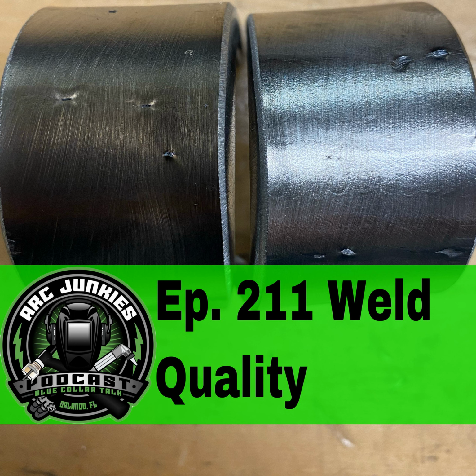Some of the stuff that causes that is our amperage being too low. If we're using shielded metal arc welding or gas tungsten arc welding, it's very simple. We can just reach over and adjust our amperage, turn that up a little bit. If we're using flux core or gas metal arc welding, that's very simple to fix too. We're just going to reach over and turn up our wire feed speed. That's going to give us some more amperage.